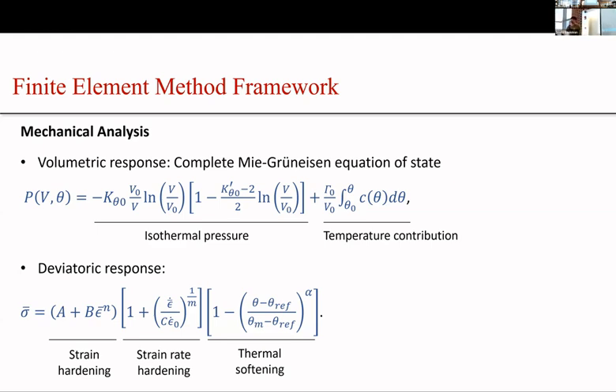Along the same lines, not sure if I understood correctly, but initially when you were talking about impedance matching and looking at Hugoniot relationships, you mentioned that your assumption is that the material is elastic, perfectly plastic. How do you put that in contrast with assuming strain hardening behavior? Yeah, so first of all, the reason why we're doing this modeling is because when we're doing the impedance matching, we have to assume it's elastic, perfectly plastic, and we don't consider the rate dependence, so we want to have a better model. That's why we are incorporating all those things in this model, so we can get a better idea of what is really going on.